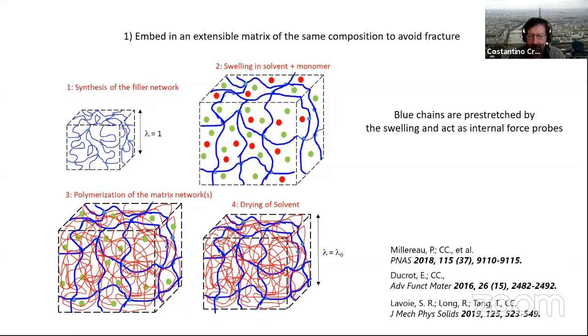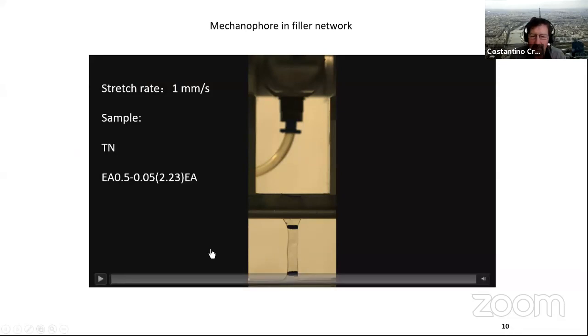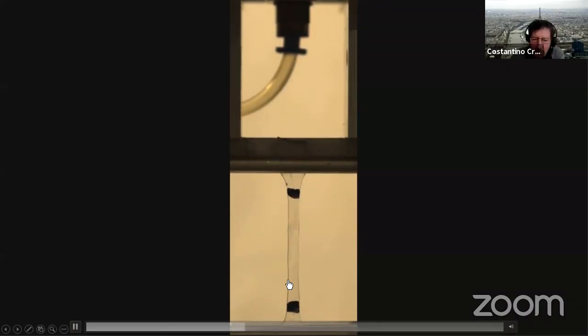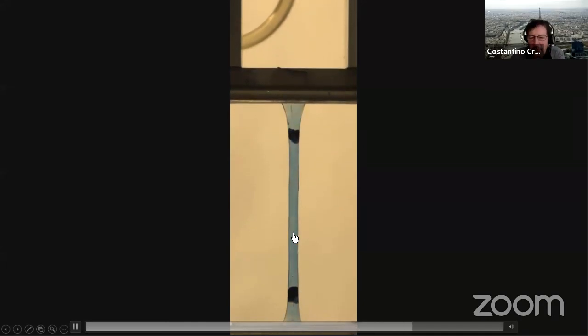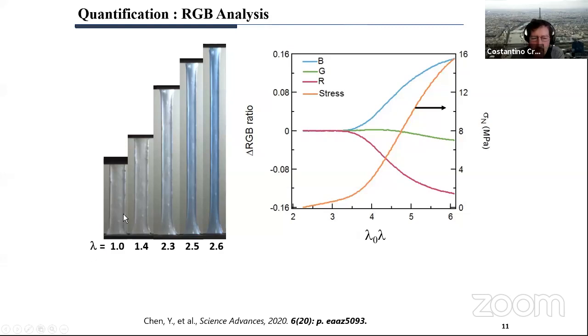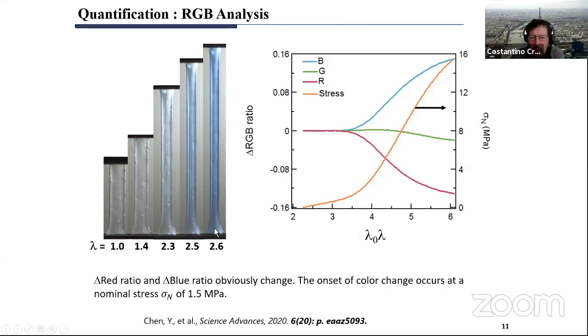Now, let me go to the next step. I'm going to show you some examples. If you make one of these embedded networks with the spiropyran, it indeed changes its light absorption. I have a little video, I hope you can see it. This is an elastic sample, you're pulling on it. And in this case, the color changes from transparent to blue. You can see that the sample becomes blue. Here are snapshots of this, depending on the stretch. As you stretch it, it becomes blue. So this is something that you can actually quantify. The data is taken with a simple RGB camera. Sorry, you can quantify the red, the blue, and the green. Of course, a spectrometer would give you even better data, but in this case, we wanted it pixel by pixel. And you can look at the stress.